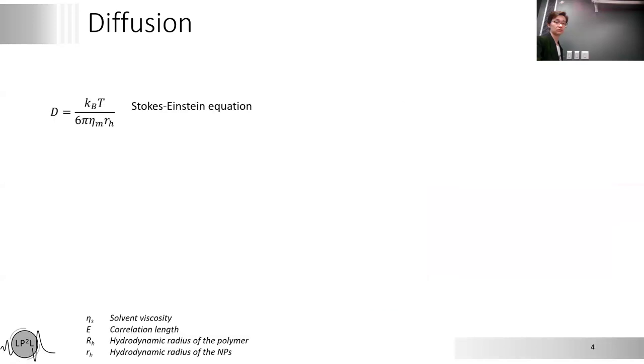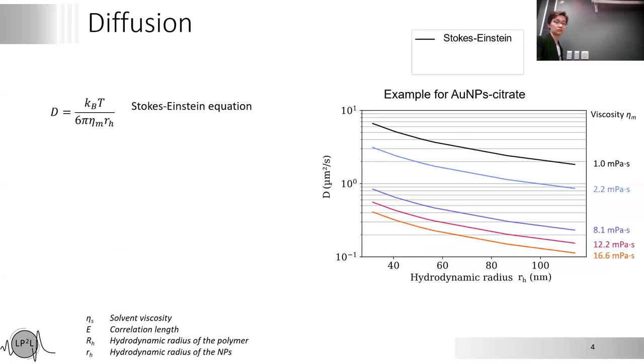Most of you may know the Stokes-Einstein equation, which allows us to determine the diffusion coefficient and which depends on the radius of the particles that we are tracking and the macroscopic viscosity. Thanks to that, we can determine in advance what the diffusion coefficient should be for a large range of radius and viscosity. However, for nanoparticles, it doesn't work. As you can see here with the dots, which are the experimental data, there is a large shift between the Stokes-Einstein data and the experimental one.